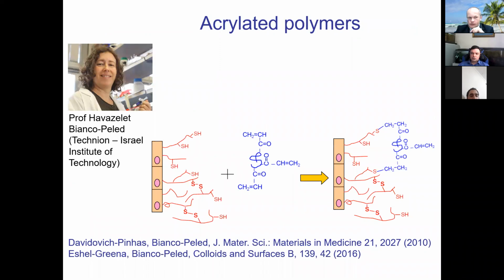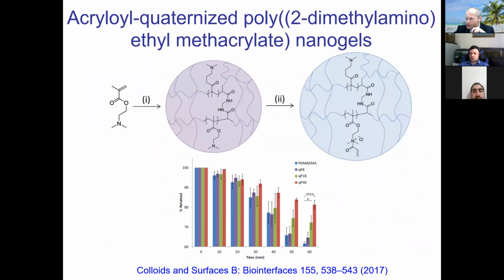But then I also was looking at the literature at the time, and I came across studies by Professor Bernkop-Schnurch from Israel, who demonstrated that if you take a polymer, you functionalize it with acrylated groups or acryloyl groups, then these polymers become also reactive with mucosal surfaces via Michael addition reactions, and this could happen under physiological conditions. I really like this idea because I knew that thiols are very prone to oxidation. So there were lots of problems with thiolated systems. For example, they sometimes result in insoluble products. So I took this idea on board and we decided to give it a try using slightly different chemistry.